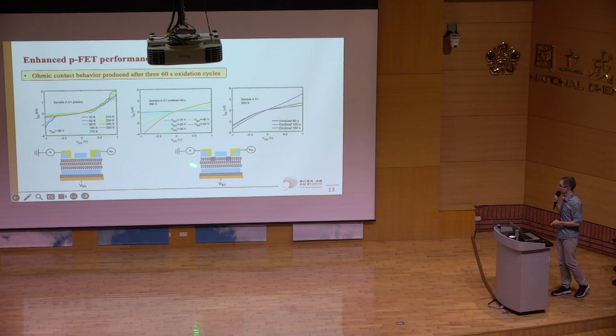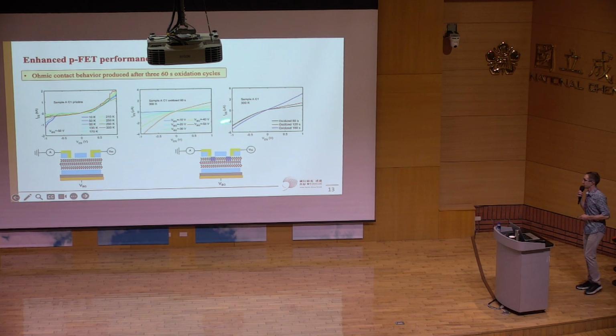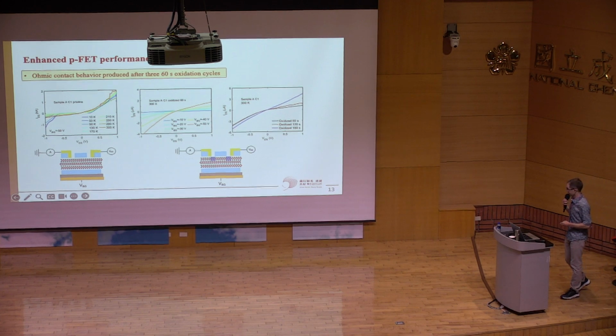remember that you've got these etched holes. So any directionality at all will mean that some regions are going to be missed during the oxidation process. So by putting it in several times with random orientation, then we get a much more uniform doping in these hole areas.